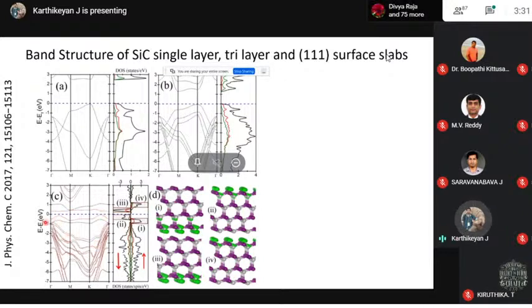And this is the zinc blende structure of a real surface slab. In this surface slab, the band gap is really small because of the surface states. We calculated the density of states, and the corresponding orbitals are plotted here. You can see that these states marked 1, 2, 3, 4 really come from the surface of these silicon carbide nanoslabs. So the band gap seems very small because of the surface states, but these can be avoided if you add hydrogen or any kind of capping atoms on the surface.